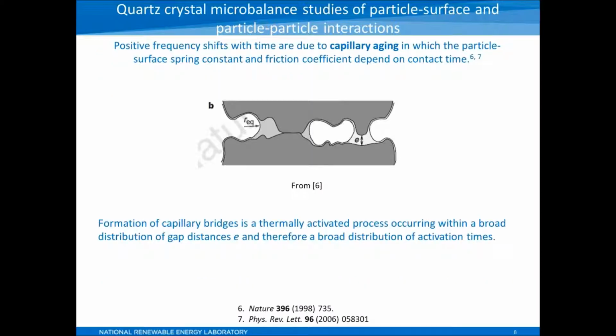So that explains qualitatively the sign of the frequency shift, but it doesn't explain the shift with time. And again, people have figured out why these friction coefficients change over time, and this is due to a phenomenon called capillary aging. This involves essentially the spring constant between those particles and the friction coefficient depending on the contact time. This is a really interesting phenomenon that happens across a large number of different types of materials, paper, glass, all sorts of things.